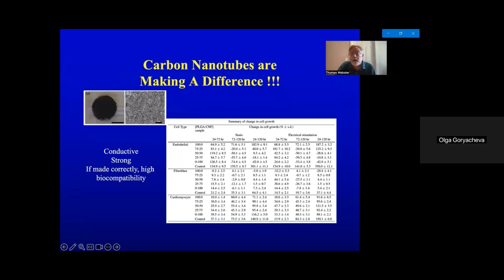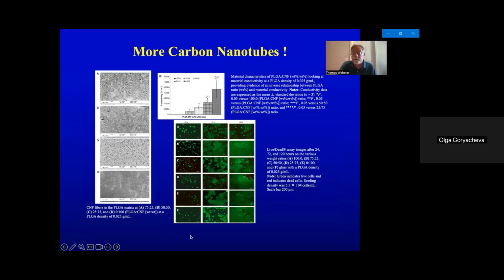Carbon nanotubes are seeing a lot of attention in this field. We're looking at endothelial cells, fibroblasts, or cardiomyocytes, and a PLGA carbon nanofiber composite material is showing, with electrical stimulation, some of the highest number of change in cell growth you can see for the highest amount of carbon fibers that were added.